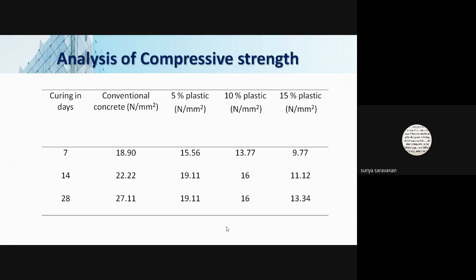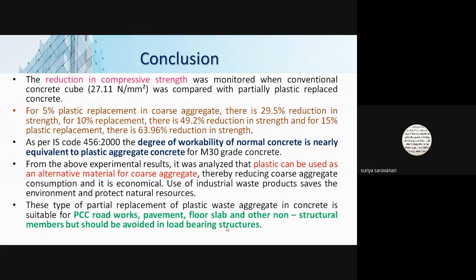So from this, what we conclude is that a reduction in compressive strength was observed with partially plastic replaced concrete. Generally, the workability is equivalent as per the IS code, but the compressive strength is decreased. So if the compressive strength is decreased, we cannot use this type of partial plastic replacement in load bearing structures. Further, we can use it in non-load bearing structures.